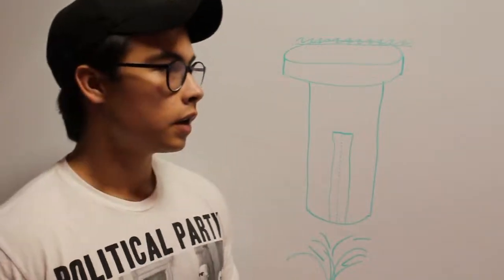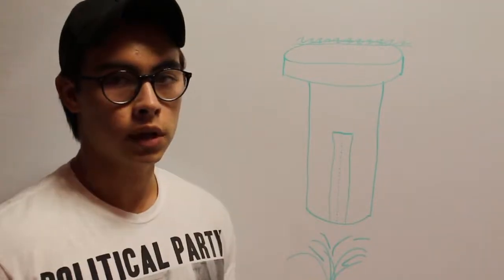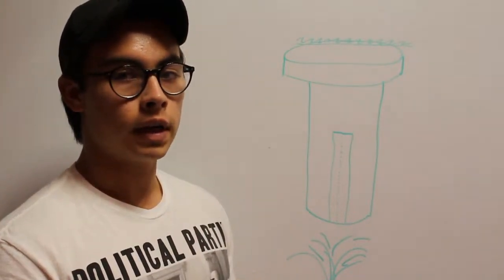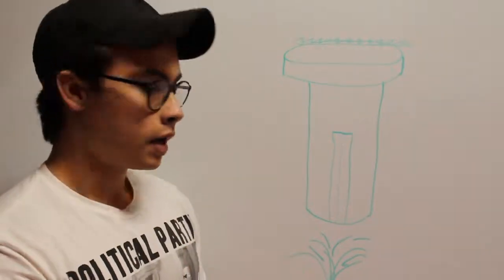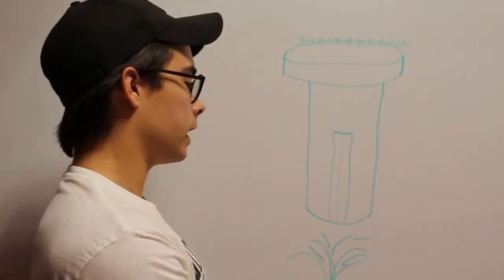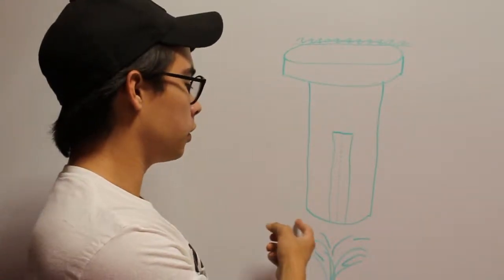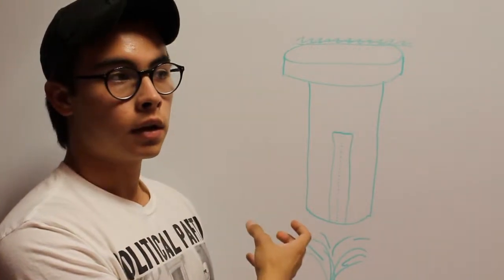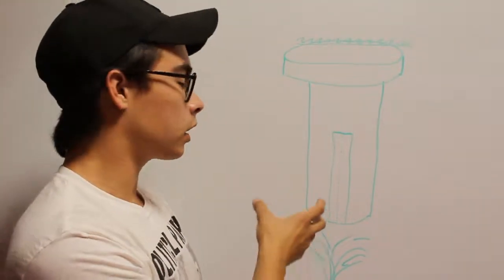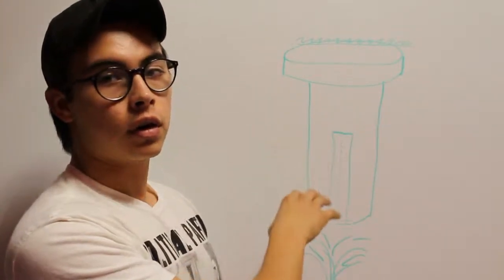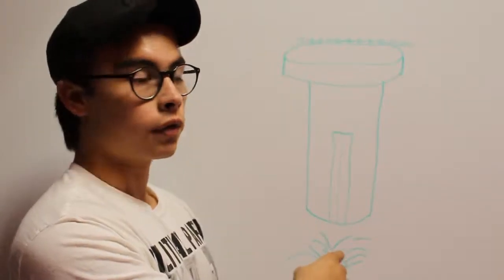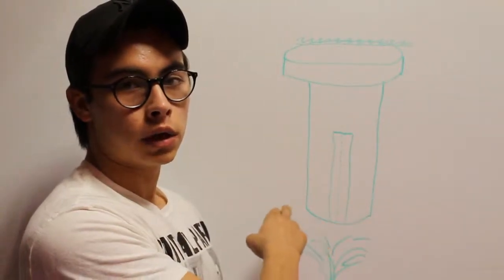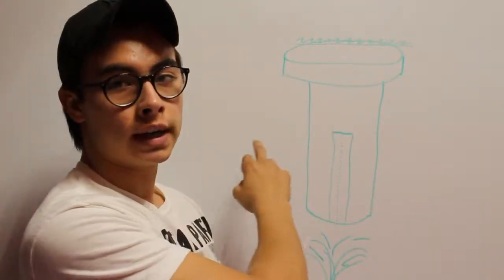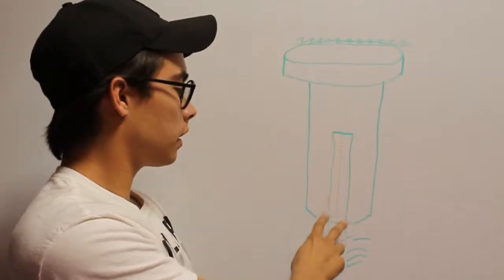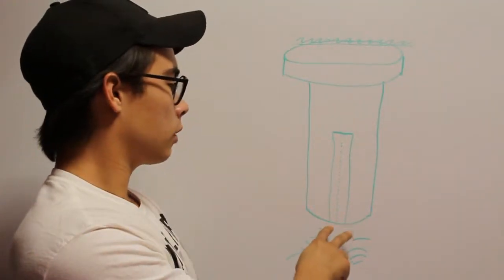Here we can see what the Jominy tester looked like. As I explained, this is the piece of metal that was given to us. We put the complete piece of metal into the oven, and after it heated, we put it in the Jominy tester. This is the water squirt I was talking about, and it hits the bottom part of the Jominy tester. So this part, in theory, should have a higher quenching rate because it got colder faster than this part that is further away from the water squirt. For this reason, here it's very likely to find martensite, then we're going to have bainite, and then we're going to have pearlite. This is the line that we made for the testing, where we did the milling and then we did the Rockwell tests.